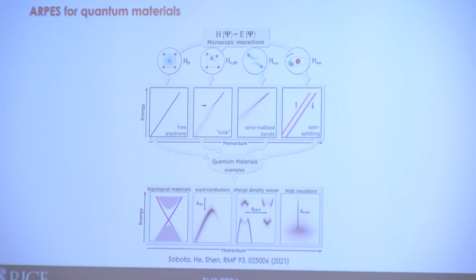So for example, ARPES has been utilized to study the spin-momentum locking of the topological surface states of topological materials. We can look at the gap produced by a superconductor. These are particle-hole symmetric gaps at the Fermi level. We can also directly look at the formation of charge density waves via the measurement of their CDW gaps, which are not necessarily particle-hole symmetric, but it should be gapped across the Q vector of your CDW.